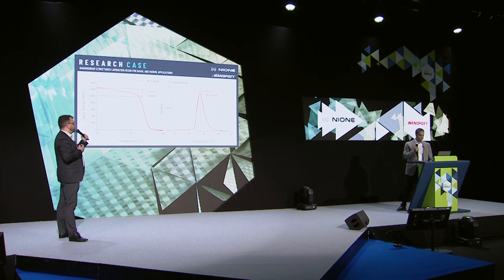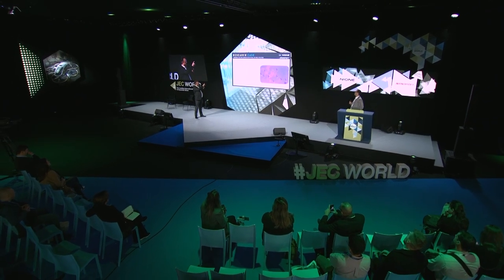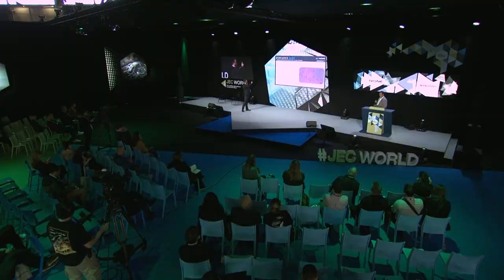This tells us that the material is tougher. Regarding UV resistance, as mentioned at the beginning of our presentation, we achieved 55% more resistant resin to both UVB and UVA, as you can see here. If you look at the right side, from the spots marked with an arrow we still have room for improvement — if we improve the dispersion of the material to the condition shown in the highlighted area, we can further improve both UV resistance and mechanical resistance.